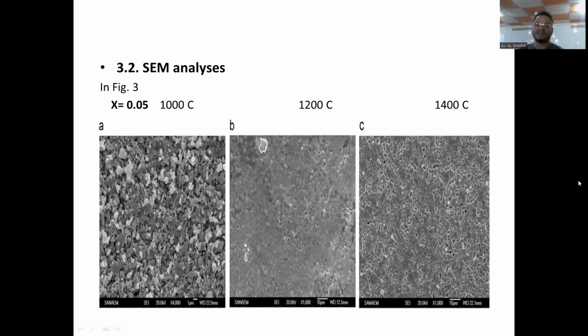In the scanning electron microscopic analysis, meeting part one talked about the microscopic image and illustrated some different grain sizes. Before increasing the sintering temperature, at 1000 °C, the nanoparticle size didn't reach more than 200 nanometers. After increasing the temperature to 1,200, it reached approximately 800 nanometers, which means multiplied by 4 times, and at 1,400, it reached something like 1.2 or 1.4 micrometers.